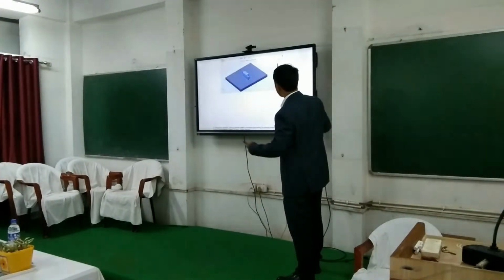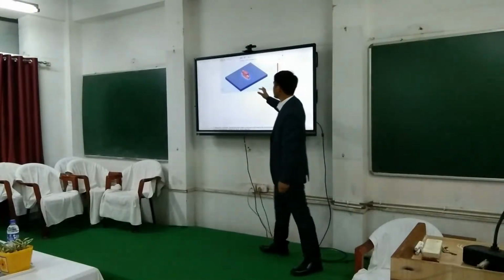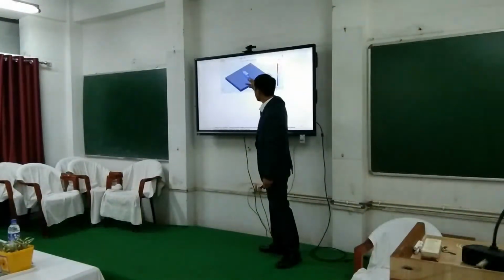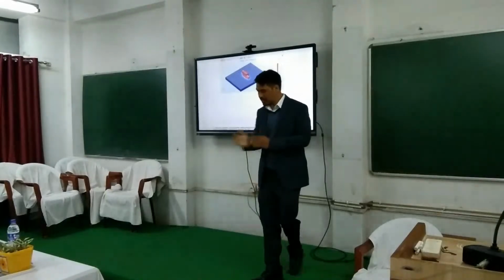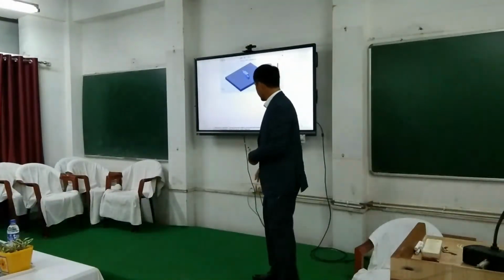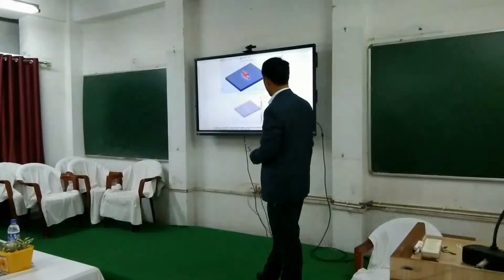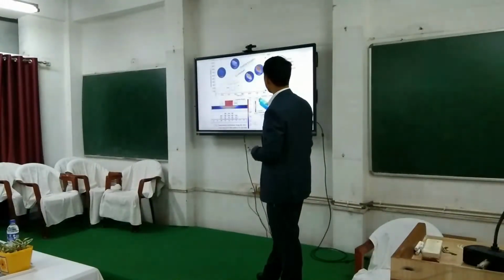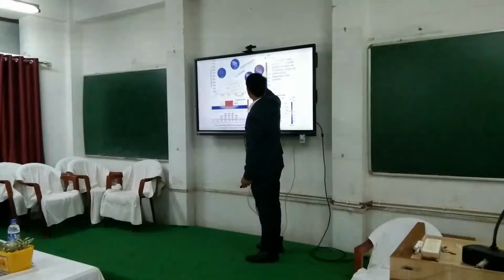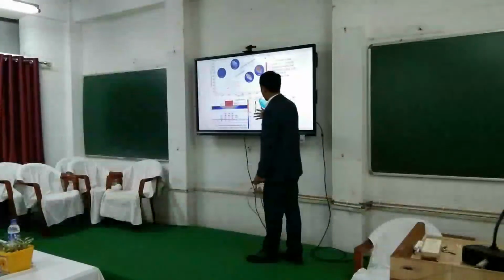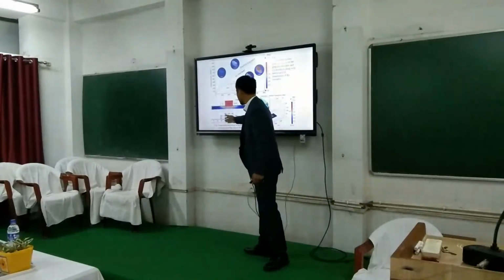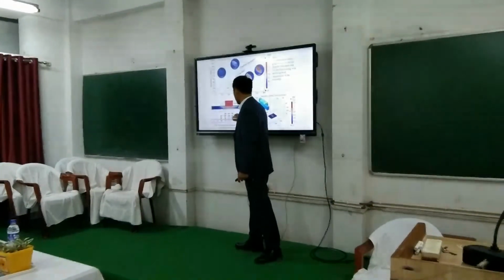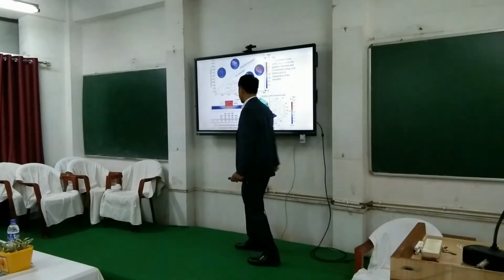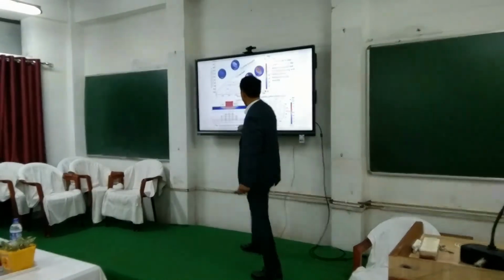With that, we also have simulated the joining methodology where we have joined two similar materials with an interlayer in between, and on top of it we have a susceptor. With the simulation we have understood that the susceptor is heating the highest, followed by the interlayer, and then the base materials are heating not much. So here you can see the cross section temperature. The susceptor is heating to around 1000 degrees Celsius. The interlayer is heating to around 900, and these are the base materials.